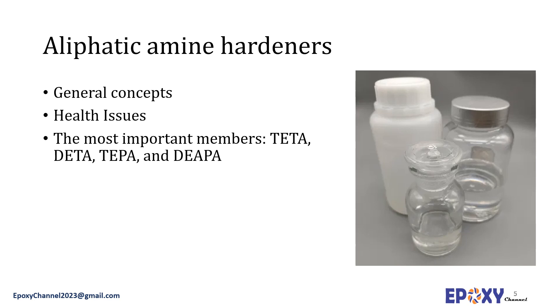Aliphatic amines generate high exothermic reactions, meaning a large amount of heat is generated during curing. Concerning health issues, these hardeners are corrosive, especially to human tissues. They are eye-corrosive — direct contact with eyes will cause severe burns and may cause permanent damage including blindness. They are often skin-corrosive as well — contact causes skin burning and may cause permanent skin damage or scarring. For each type of amine, the SDS document should be carefully reviewed before handling.